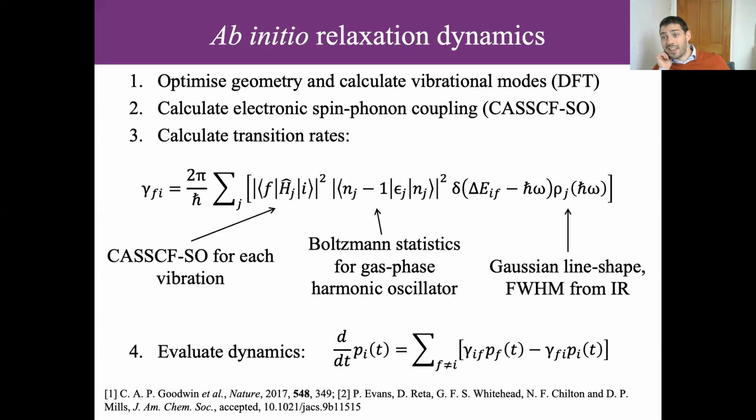Definitely, but you know, we're still not down at that low temperature region yet. Once we get there, then absolutely we need to consider dipolar coupling. I would argue that super exchange is probably very small because these are not covalently bound between different metal ions. So I would imagine that it's mainly a through space dipolar process. But yeah, that could be included. You know, we could think about doing that in some way or another. Yeah. But in order for you to approach the low temperature, you really need to work out these phonons.